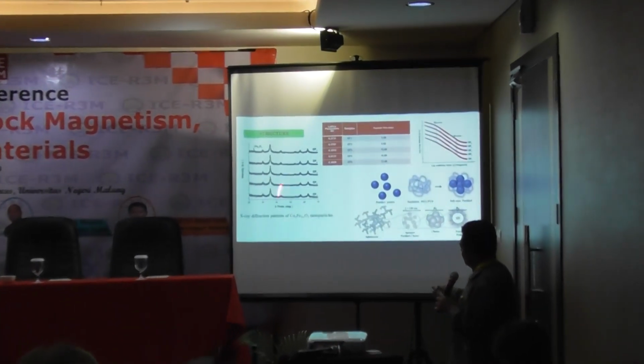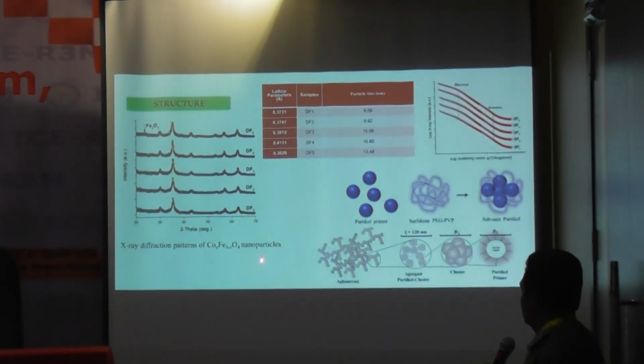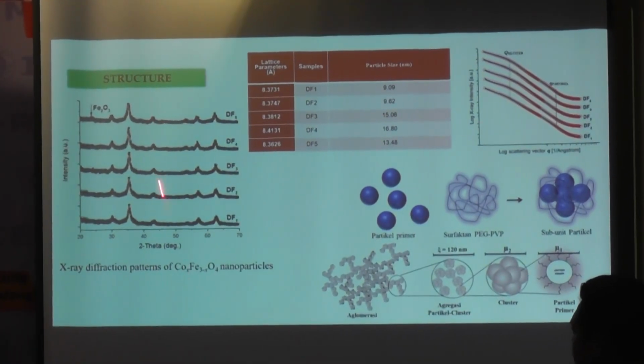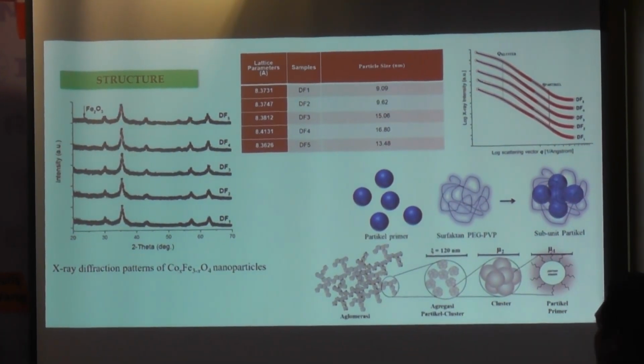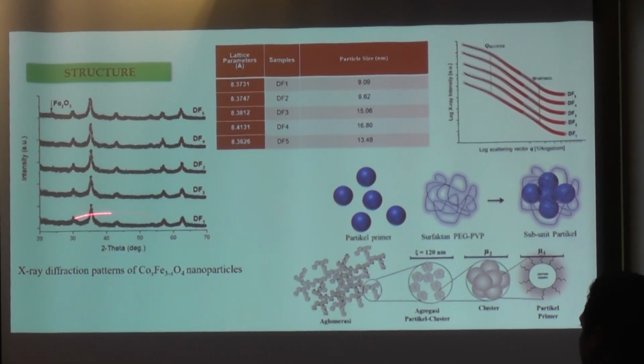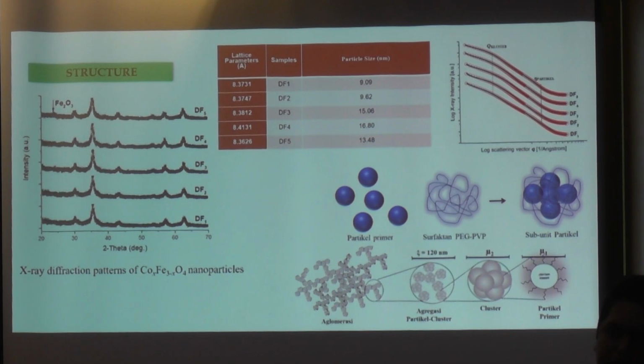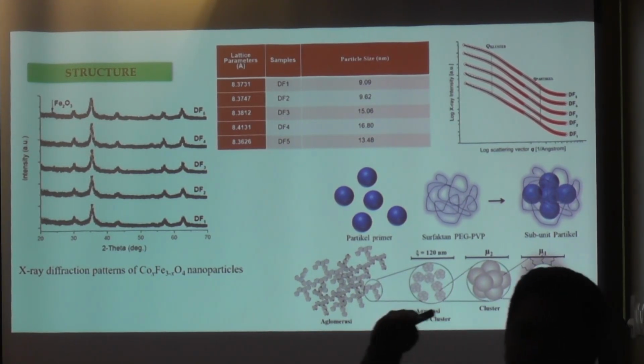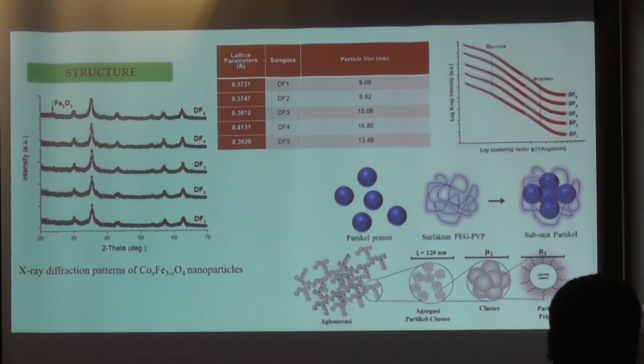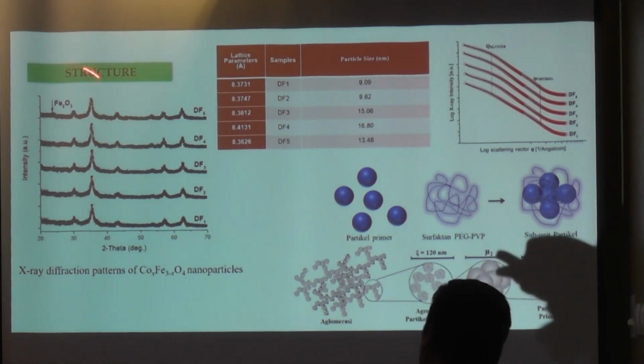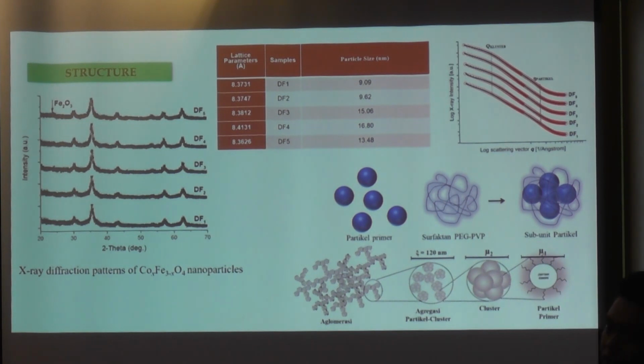And the next data, this is the interesting data. We also mix some doping with cobalt. The higher the cobalt doping also makes the particle size higher because of the difference in ionic radii. But the problem is, if we mix some doping at the highest composition, there are some extra peaks that indicate it will produce another compound. We call it Fe2O3, maghemite.